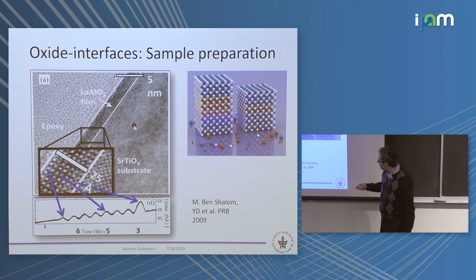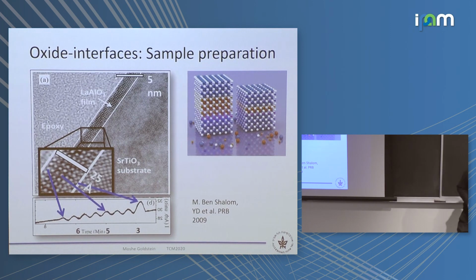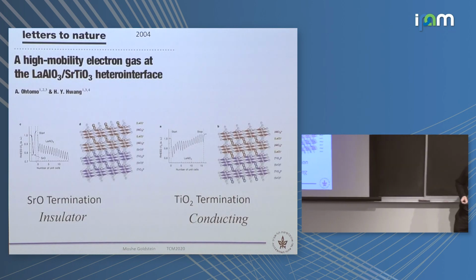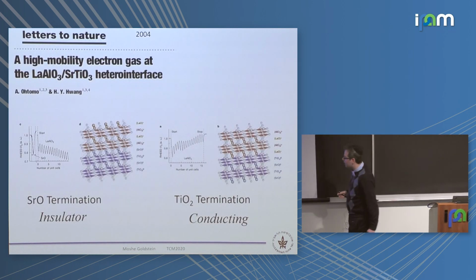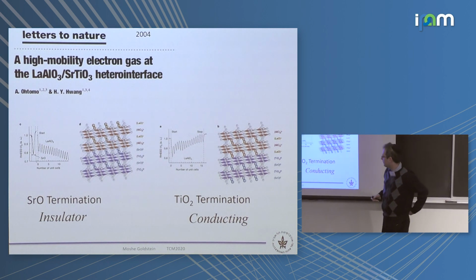So this is the STO substrate, and this is, I think, 8 layers of LAO grown on it. You can actually follow the diffraction pattern and grow as many layers as you want of LAO on top of the STO. And now, in this seminal paper by H.Y. Hwang, something like 15 years ago, they have shown